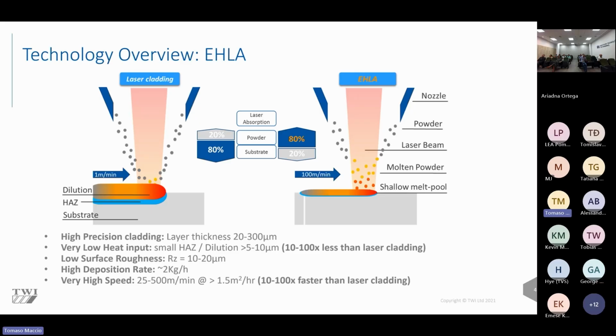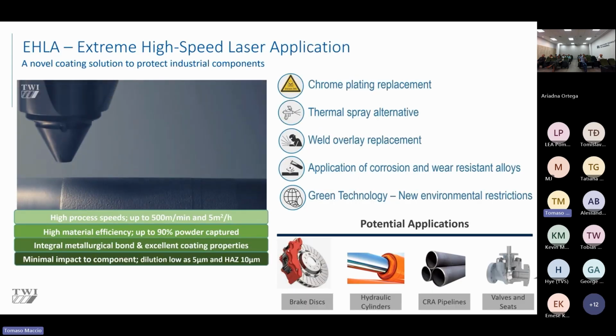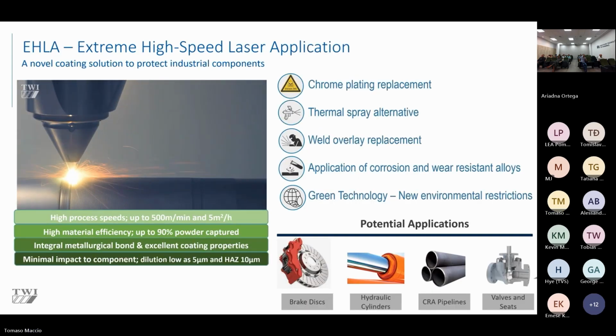So we can do high precision layers. We can do anything from 20 to 300 micron layer thicknesses with very low heat input, anything from 5 to 20 micron heat affected zone, with a very nice surface roughness as well, and high deposition rates. We're able to go at high speeds as well, like described previously, so 25 to 500 meters per minute. This is EHLA in process.